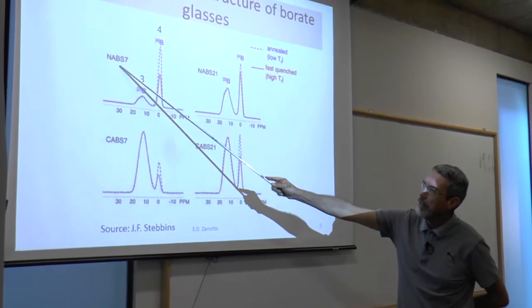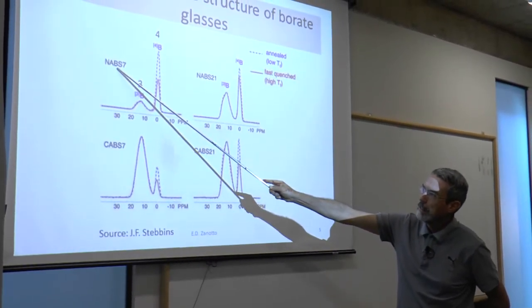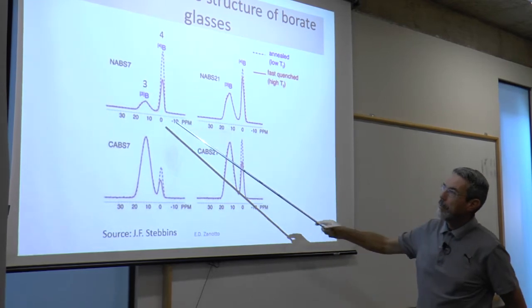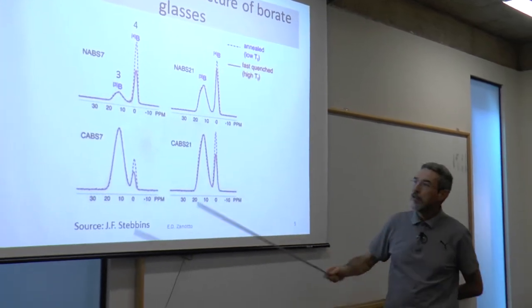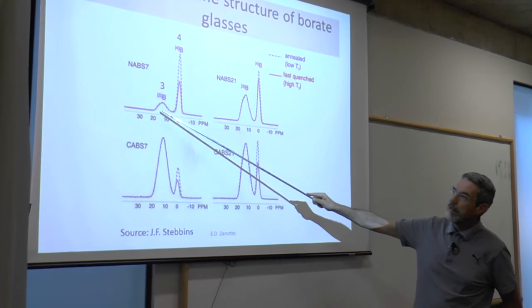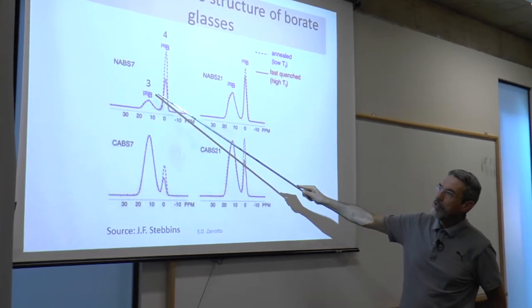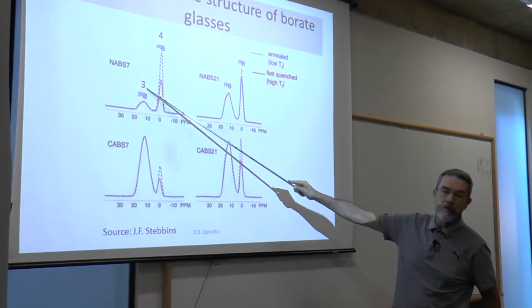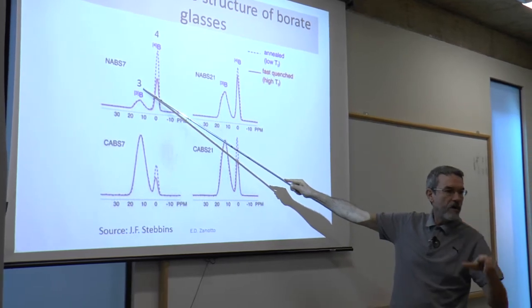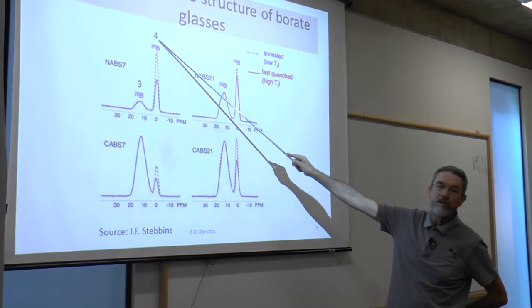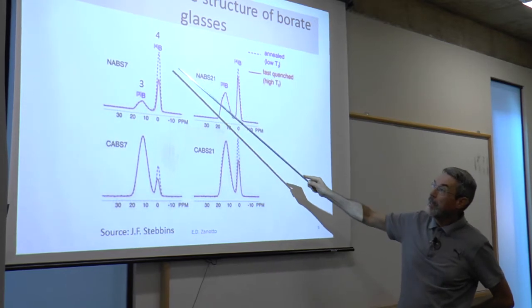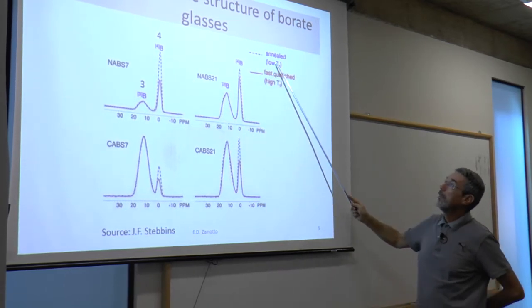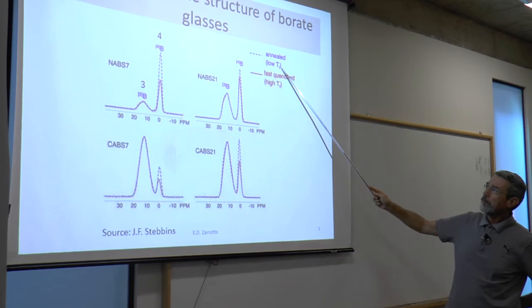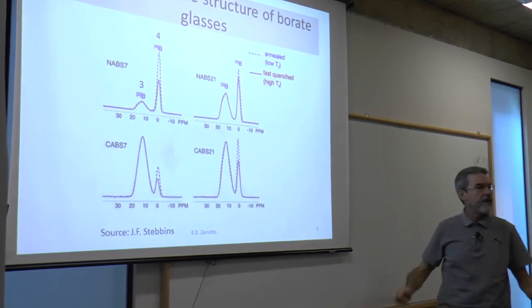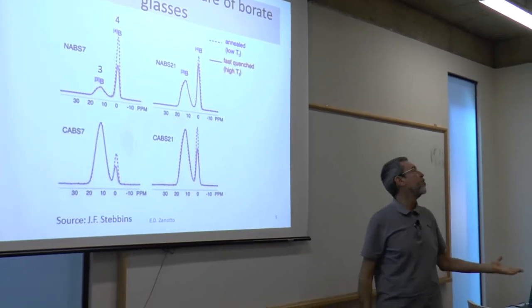Borate glasses have a lot of boron, and boron is very good for NMR. So if you do an NMR experiment, you can distinguish boron at coordination 3, boron bonded to three oxygens, from boron at coordination 4. And you see the annealed material, annealed means low fictive temperature, or slow cooling rate.